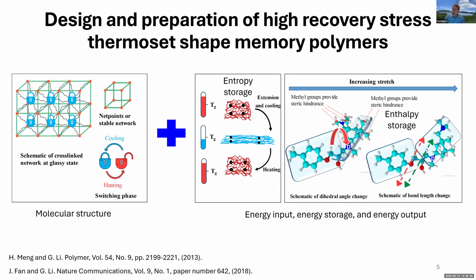During the pre-stressing process, the polymer network will be aligned along a certain direction. This is a figure showing that. You can see this initial random configuration. After stretching, it becomes ordered so that the entropy is reduced. Of course, entropy reduction will be able to store a certain amount of energy. Later when you trigger the shape recovery, the entropy will increase and the ordered molecular structure will go back. So you will see the shape recovery.